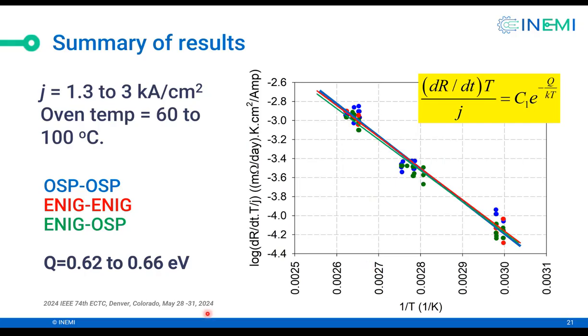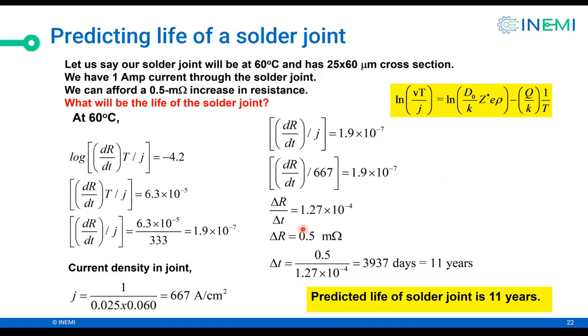So we have three finishes: OSP, which is blue data points, ENIG, which are red, and ENIG OSP, which are green. And you can see they essentially fall all on the same plot. And the activation energy is 0.62 to 0.66. Activation energy is the slope of the line. So all these three lines have very similar slope. So the conclusion is that the surface finish doesn't play a critical role in electromigration.